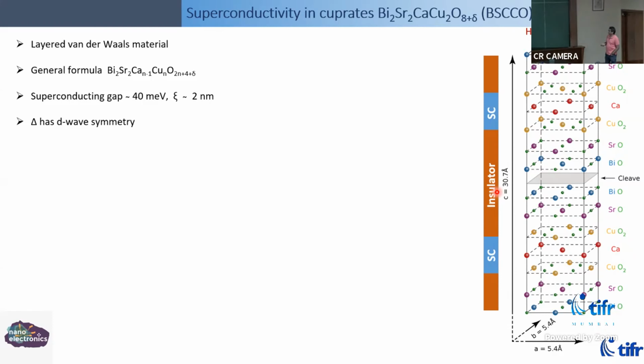We don't know a lot about the microscopic mechanism, but what everybody in the community agrees on is that there is a superconducting gap, which is large. It has a TC of about 85 Kelvin, above liquid nitrogen, and its coherence length is very short, which is typical of these type 2 superconductors. The distinguishing feature of many of these high TC materials is the symmetry of the superconducting order parameter.